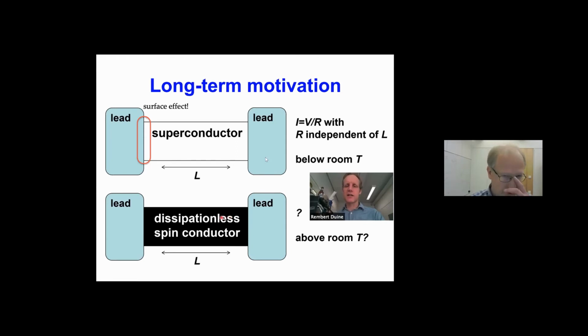Rembert discussed yesterday in his tutorial the desire to realize a dissipationless spin conductor where the resistance that you measure, or the spin resistance, is independent of the length. He compared this to the case of superconductors coupled to two leads. Indeed, in this case, in a long superconductor, the resistance is independent of the length. However, there is still a surface effect related with the conversion of the quasi-particle currents to supercurrent.